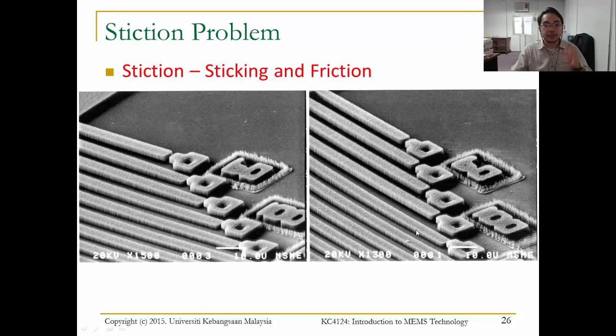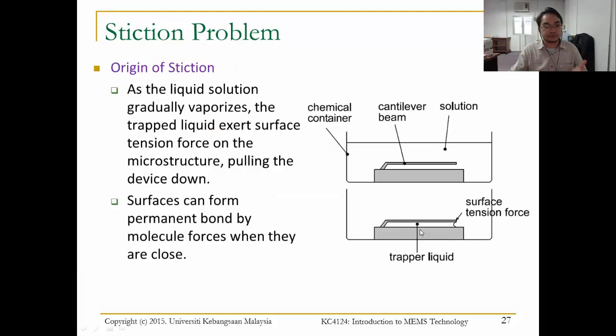Now, this problem is due to the fabrication process. Alright? Now, what is the origin of stiction? During the process, as the liquid solution gradually vaporizes, the trapped liquid exerts surface tension force on the microstructure, pulling the device down. Okay, surfaces can form permanent bonds by molecular forces when they are close.